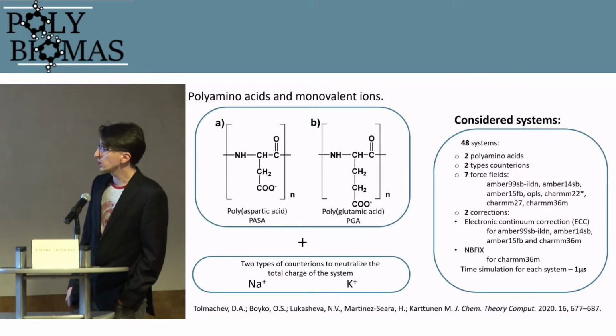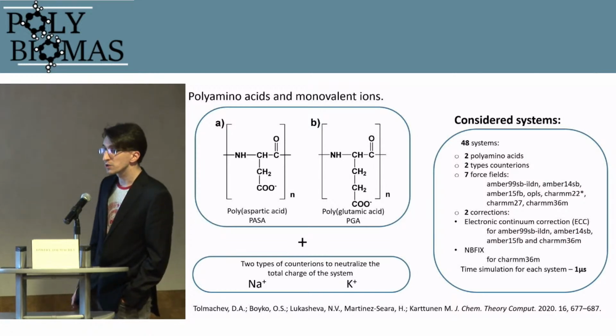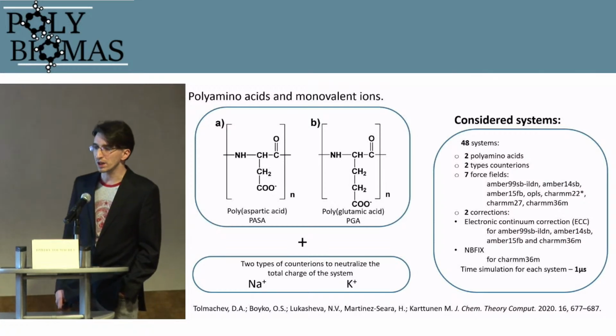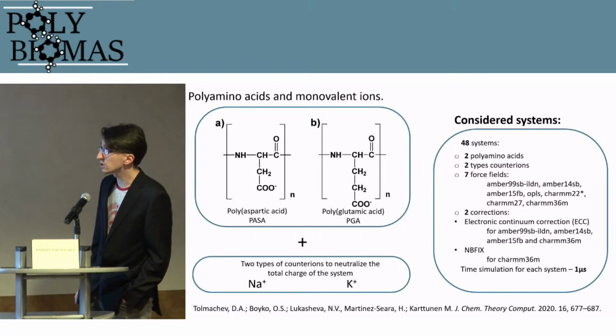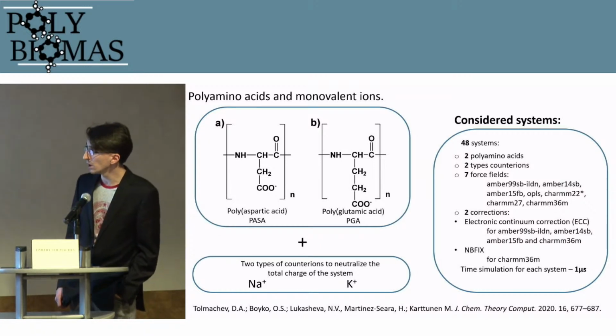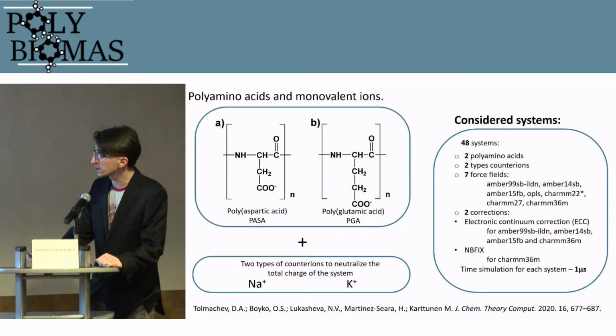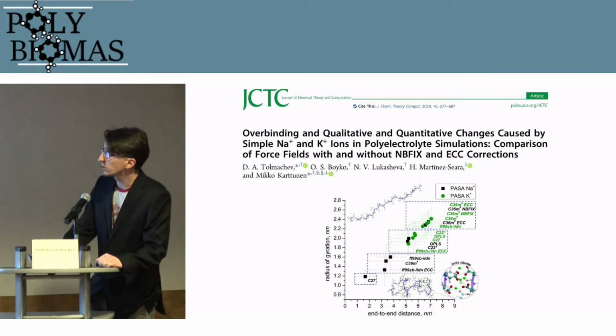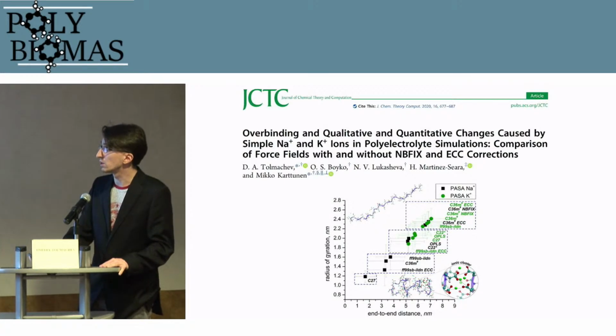So in our simulation, we considered 48 systems. We checked 2 polyamino acids, as I said, and 2 types of counterions, sodium and potassium. From experiment, it's known that at relatively low concentration of salt, the effect of sodium chloride and potassium chloride on these polyamino acids should be the same. We checked 7 force fields, with 2 corrections in some cases, and each simulation was performed for 1 microsecond. It is important to know that some of the results were published in our recent paper in the Journal of Chemical Theory and Computation, and this paper found a very good response from the scientific community and has a good number of citations.